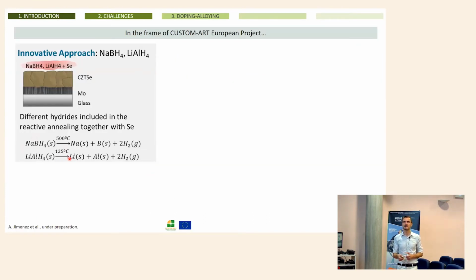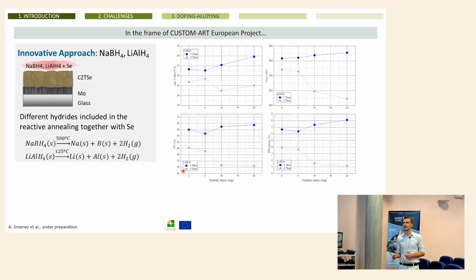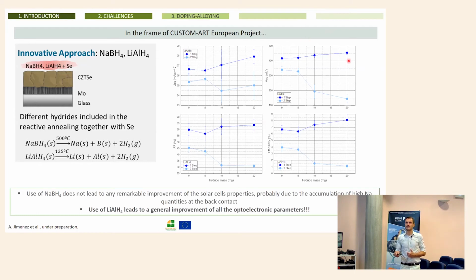Basically, these hydrides tend to decompose at different temperatures, giving the free elements, including hydrogen, lithium, and sodium. And we had a very nice surprise with this, because we observed that in some cases, working with lithium, we have a really huge improvement in the VOC of the material. Also, the other properties are boosted, including the efficiency, of course, but mainly the VOC, which is the most complicated one to improve.